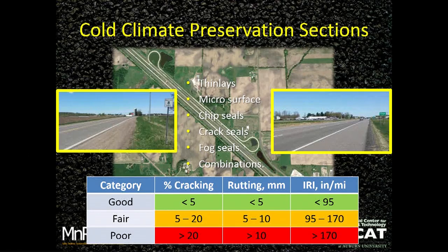So what we found with our research, we measure all of that in our test sections, but roughness really doesn't change until a pavement is in a failure condition. Otherwise, it's pretty flat. Rutting doesn't change again unless something's going wrong, you've got a material deficiency, or it's in a failure condition. So what we're seeing more than anything else is the return of cracking in our test sections. And so that's the thing that you hear us talk about the most when it comes to implementation of our